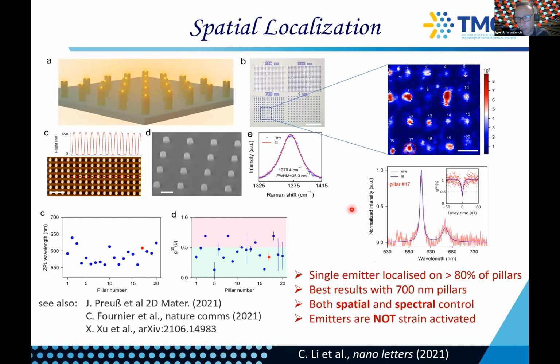So we now have spatial and spectral control. And an important point to make here is that there are no strain-activated emitters, which means that there is no strain that affects whether they are formed or not. It's really a localization, most likely simply optical, because the pillars will just enhance the emission exactly at the top. Okay, so this is good.